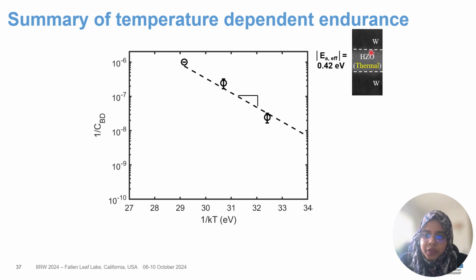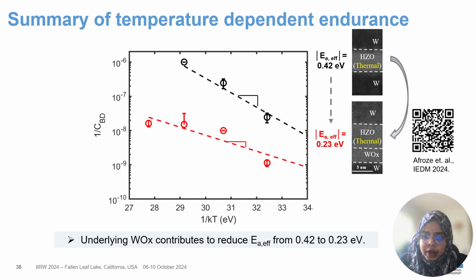So we first start with our thermal ALD device, and we saw that the effective activation energy is 0.42 electron volt. Next, what we did is we intentionally deposited tungsten oxide at the bottom interface and then deposited the same thermal HZO film on this one. And here what we are seeing is that the effective activation energy was suppressed from 0.42 to 0.23 electron volt.